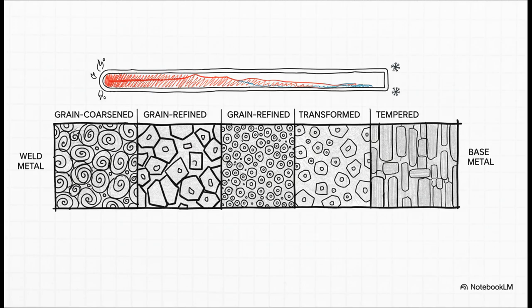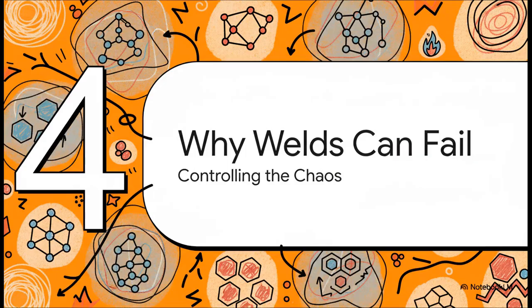Right next to the weld, the intense heat makes the grains grow large and coarse, which can be a weak spot. A little further out, the temperature is in a sweet spot that actually refines the grains, making them smaller and stronger. It's like a microscopic timeline of heat's impact, all within just a few millimeters. So, creating this complex landscape of zones is this incredible thermal balancing act. And if that balance is off, if the metallurgy isn't controlled with absolute precision, this rapid heating and cooling can introduce some really devastating weaknesses that can lead to failure.